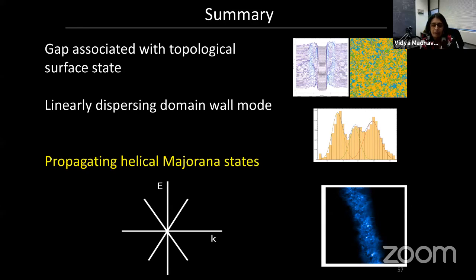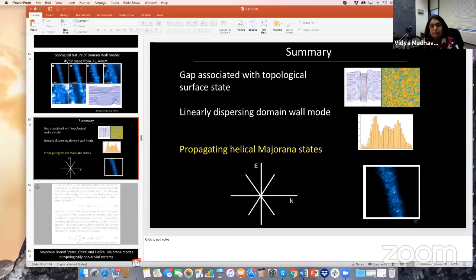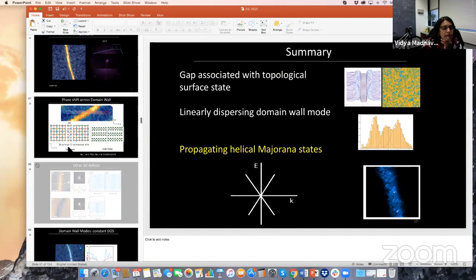Your question is exactly what Jay was asking earlier. How do we know that the domain wall is not simply killing superconductivity entirely? So we did also check other kinds of domain walls. And what we find, in this material as well as another material, which is FeSe, is that in all of the cases that we saw for any kind of one-dimensional defect in this crystal, other than this one, we see in-gap bound states that exist. They look like sharp peaks. I removed those slides, I think.